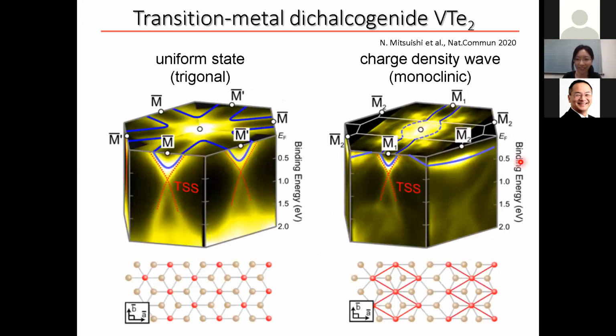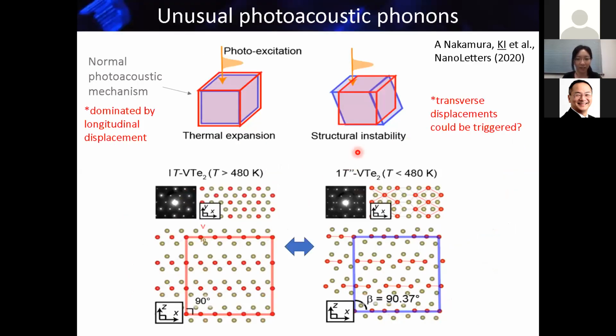And this is a side note, but we also measured ARPES in this material, and we found a very big change in the electronic structure like this. Some bands show very flat bands, which correspond to the vanadium trimers, and then this topological surface state completely disappears. So it's another story, but from this we can say that this CDW state is strongly coupled to the electronic structure and gives us the chance that we can control this CDW state by using light. Okay, so our first idea was to break the CDW by the optical pulse and drive some structural instability.